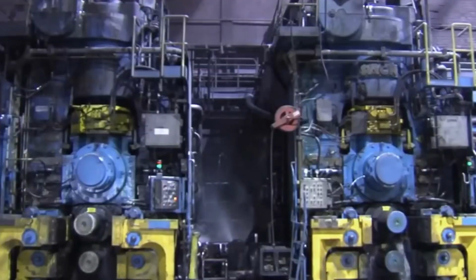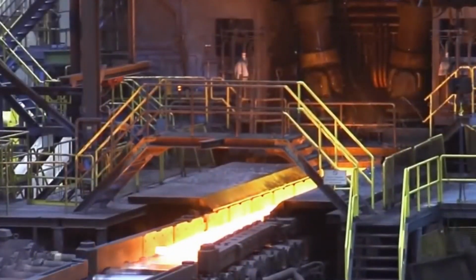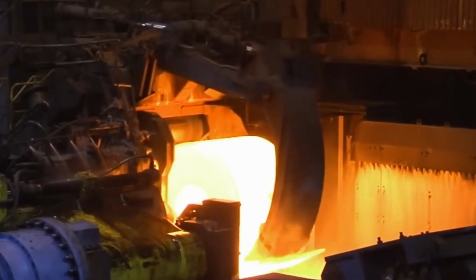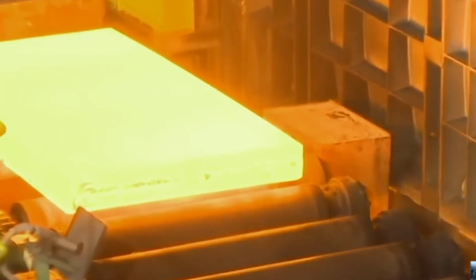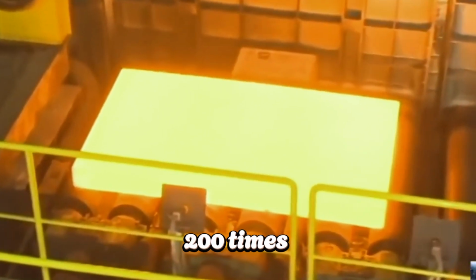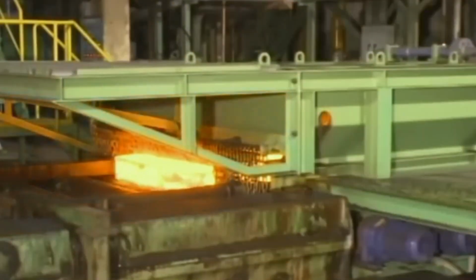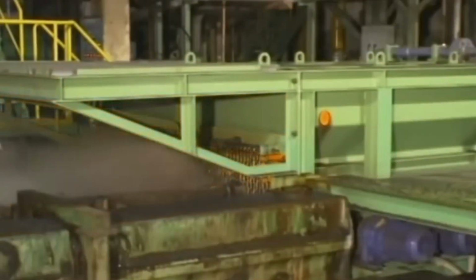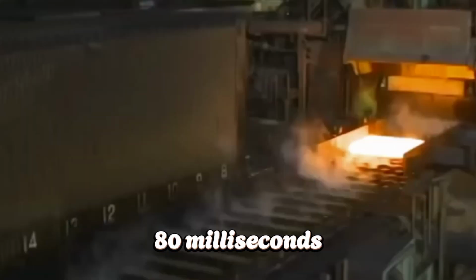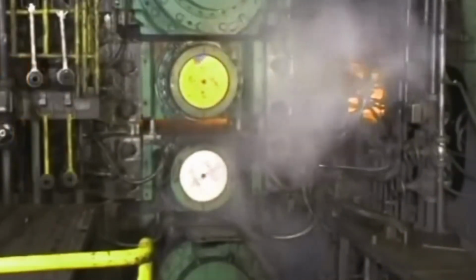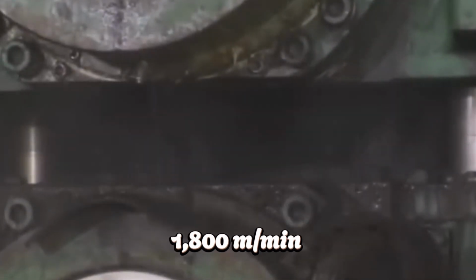One digit decides everything. AGC samples thickness every millisecond. Interstand tension loops update 200 times per second. Roll bending actuators correct crown within 80 milliseconds. Oil film thickness sensors prevent roll welding. Chatter monitors detect third octave vibration and retune tension in real time. The entire grid keeps 1,800 meters per minute steel stable.